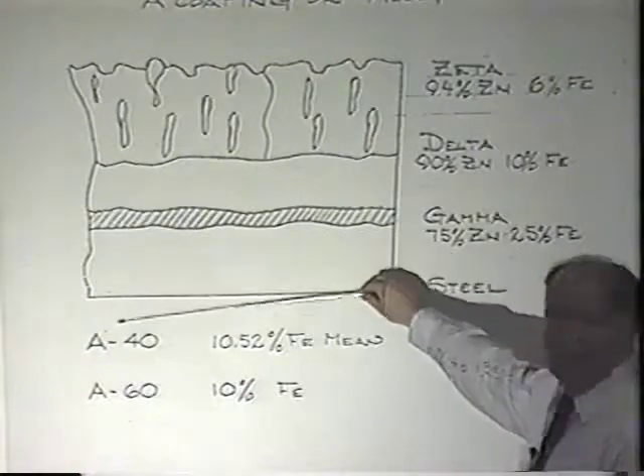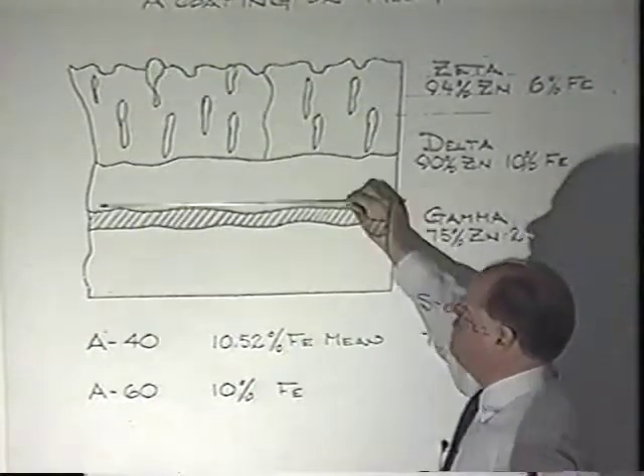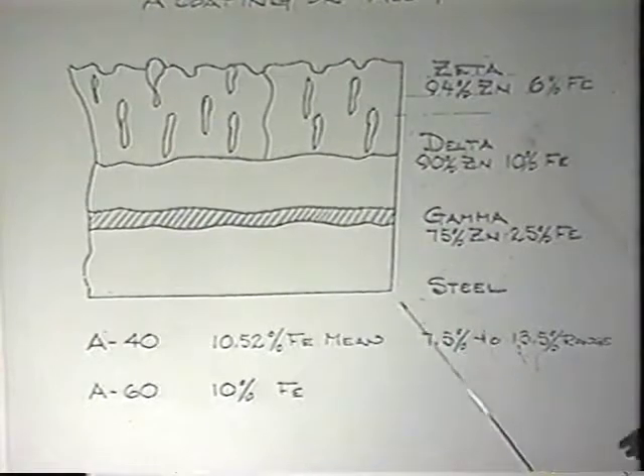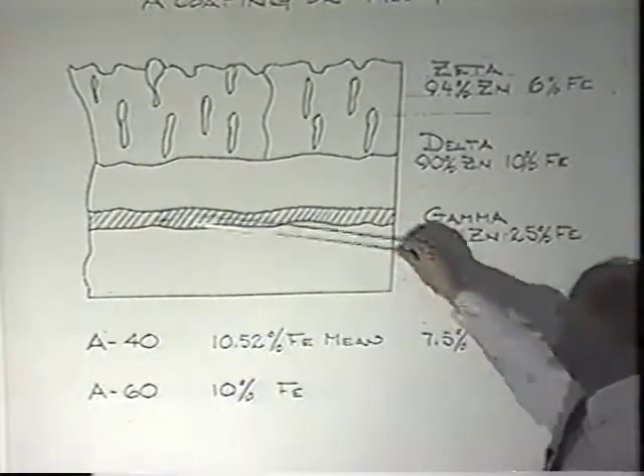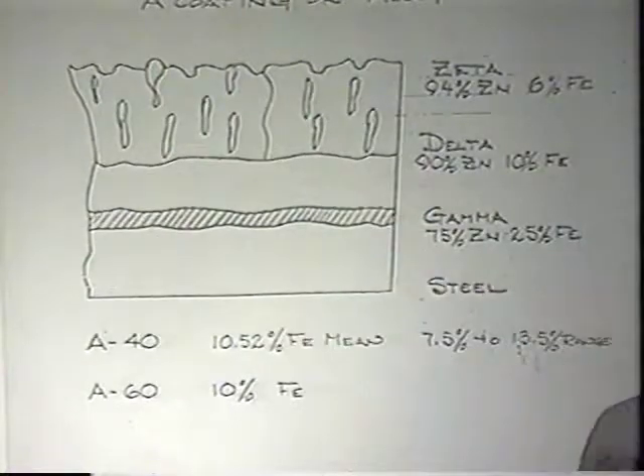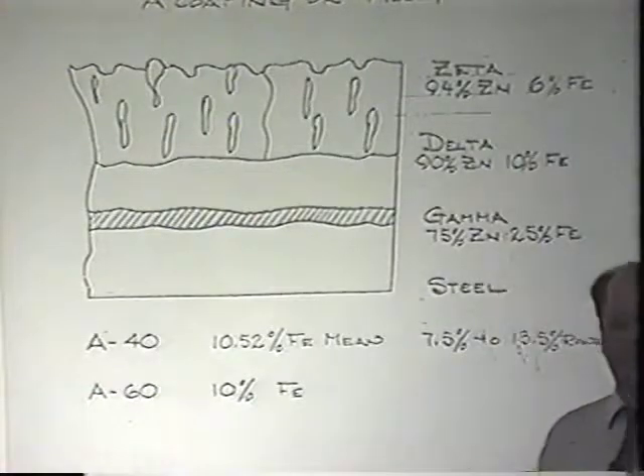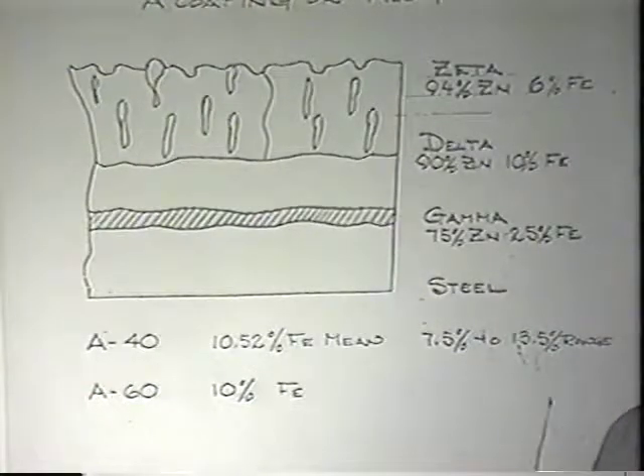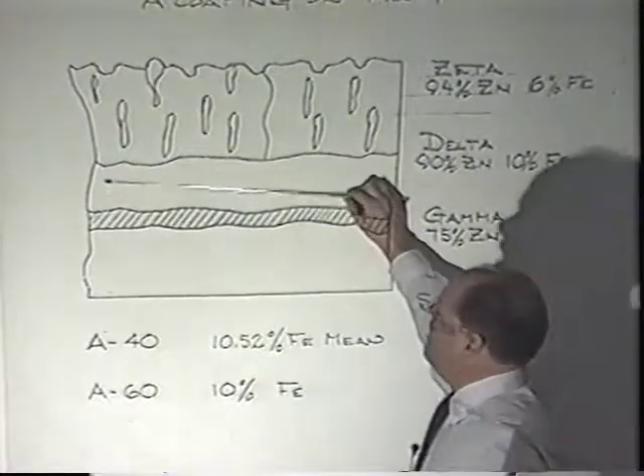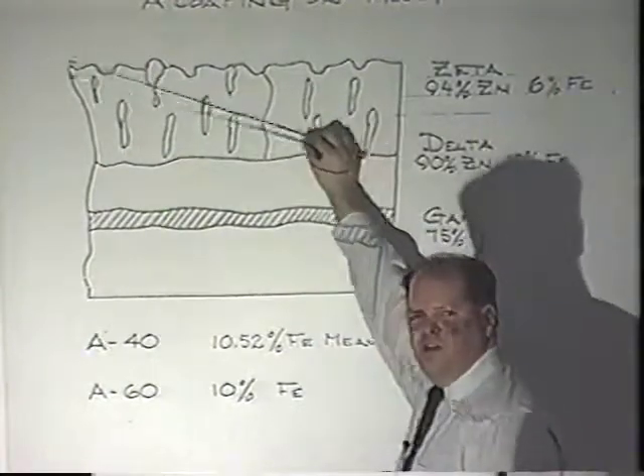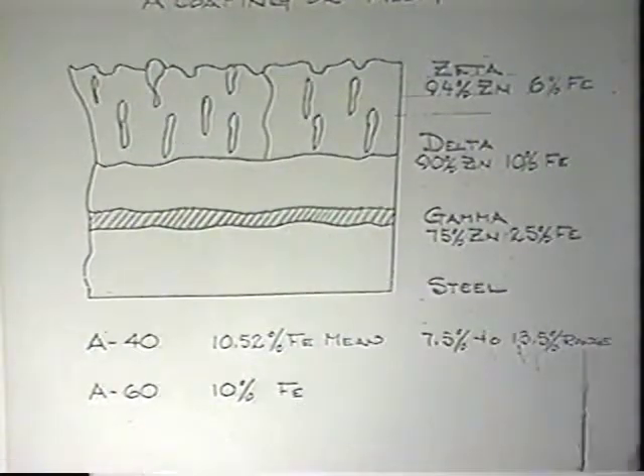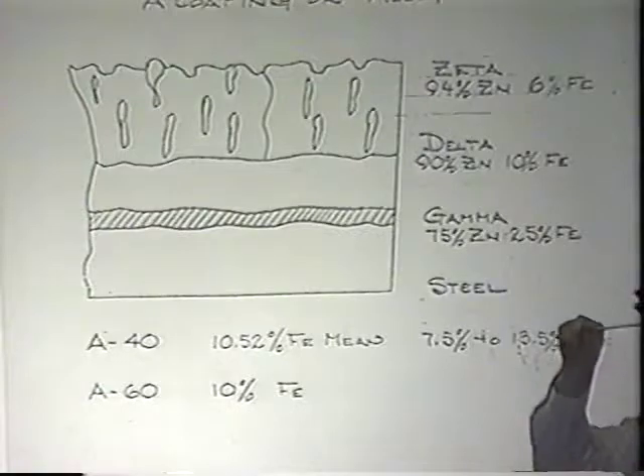What we've done is, here's your base metal steel going through the line. There's where your zinc was that was stuck on the steel when it went through the zinc bath. That little bit of alloy growth happened just like it did on the last slide that I showed, basically to form the galvanized. Before that could solidify, while you still had molten zinc on there, what we do is heat it up to about 1025 degrees for maybe only about 10 seconds and allow that alloy growth to continue all the way to the surface. So that little alloy layer that was making the zinc stick to the steel, we actually just kept growing. So it went all the way to the surface.